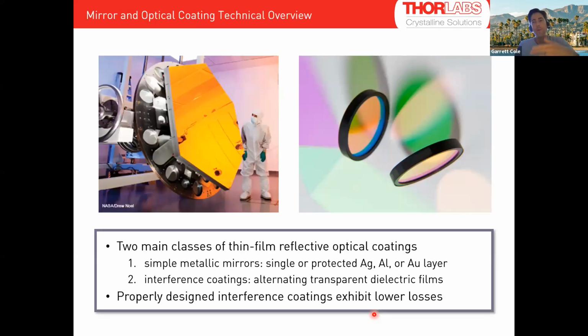So now I'm going to jump way back, and I think for most people this is going to be very basic, but I'm just going to give an overview of mirror technologies. So there's two main classes of thin film reflective optical coatings. The simplest is going to be just single layer metal mirrors, right? So this could be silver, aluminum, or gold with or without a dielectric protection layer. You can get relatively high performance in these, let's say reflectivities at the 93 to 98% range, but there's some major drawbacks. So one, you're not going to be able to transmit light through the metal. It's opaque, obviously. Your reflectivity is going to max out at something in the high 90% range.